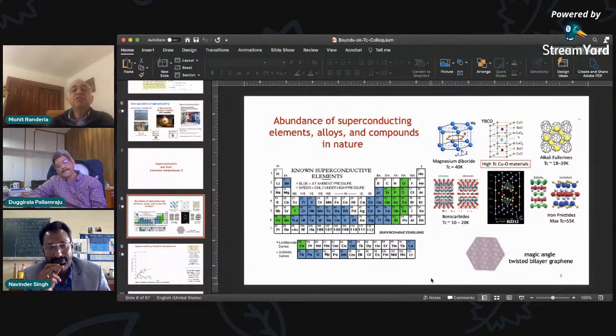Because if you look at the high temperature cuprates, they don't avoid oxygen. It's an essential element there. They are very close to magnetic Mott insulators. They don't avoid magnetism. They're not three-dimensional or cubic. They are tetragonal or orthorhombic materials which are layered. So every one of Matthias's rules is violated. So I'm afraid we just simply don't have such rules of thumb.